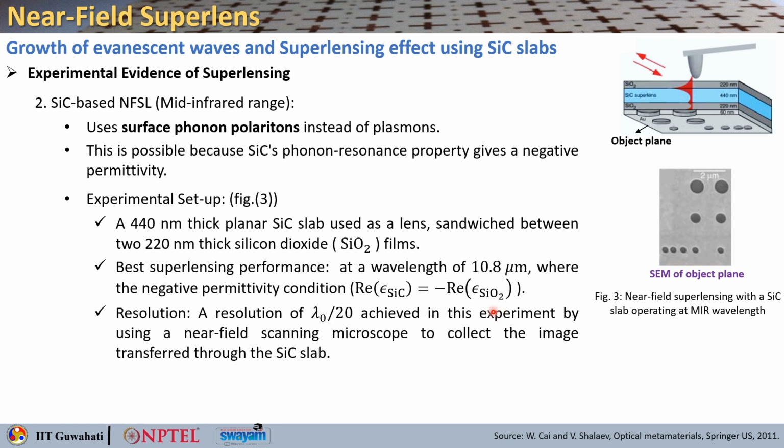So, what was the result? A resolution of lambda naught by 20 was achieved in this experiment, which was obtained using a near field scanning microscopy that could collect the image transferred through this silicon carbide slab.